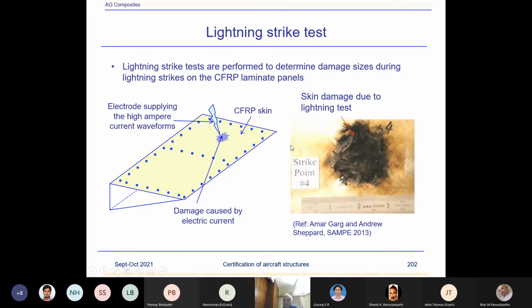in Seattle they were impacted with different voltage and current levels, and this is just one strike point showing a large damage. You can see the scale, and I don't remember what the current and the voltage were here, as this is not in the paper presented. Whatever information is in the paper is only what I can state here. So from this scale, you can see virtually almost 3 inches of damage. It's a severe damage.